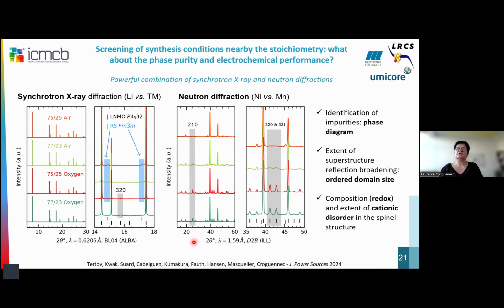But it is also interesting to highlight that, depending on the conditions, you can see that the superstructure lines associated to this ordering between nickel and manganese have very different broadenings, moving from, I would say, sharp lines to much broader lines, and even here much more diffuse. And that, you will see, will be associated to the size of the ordered domains.